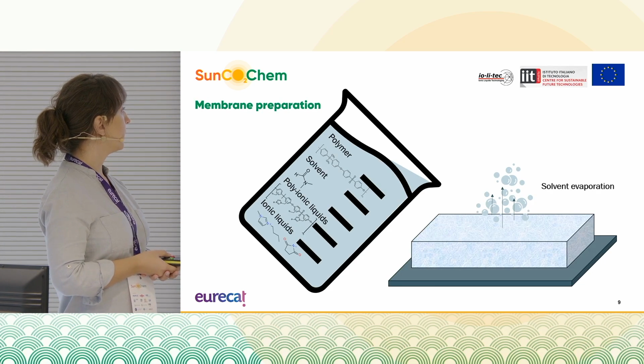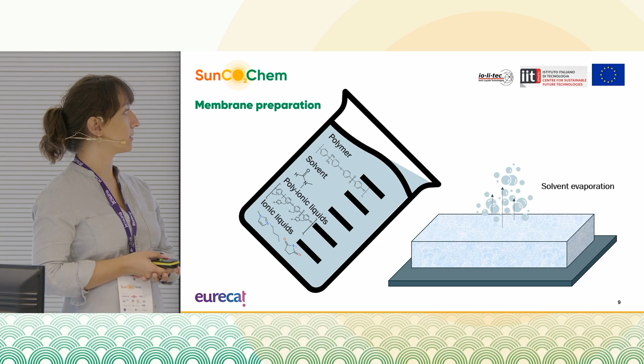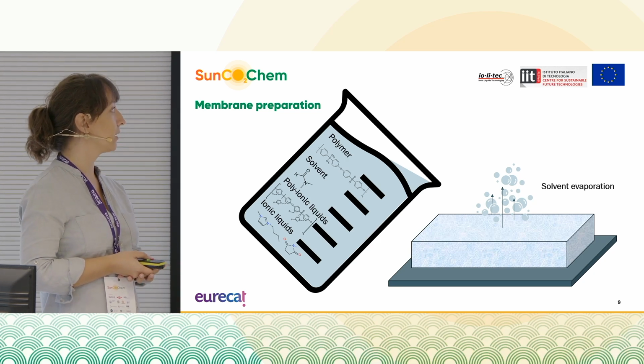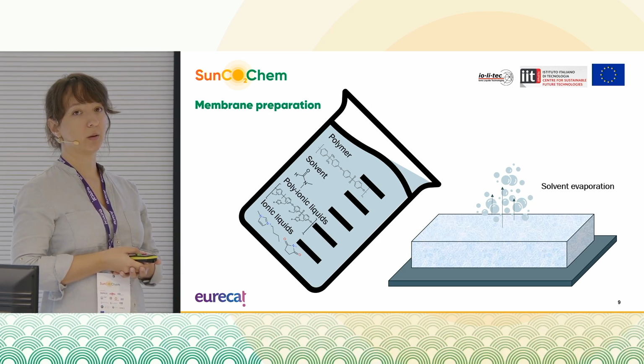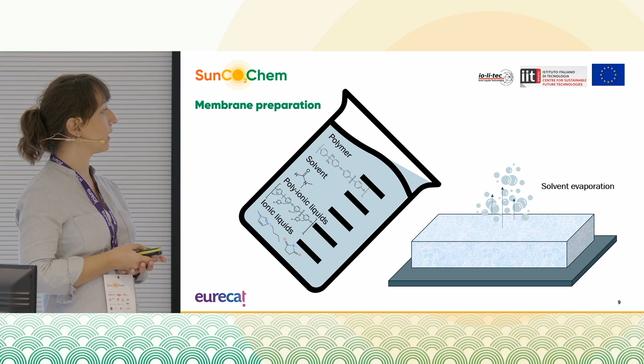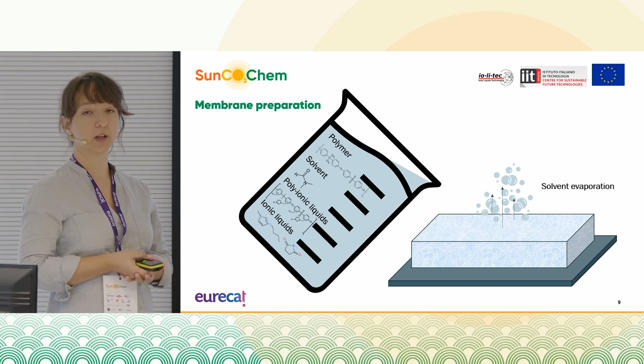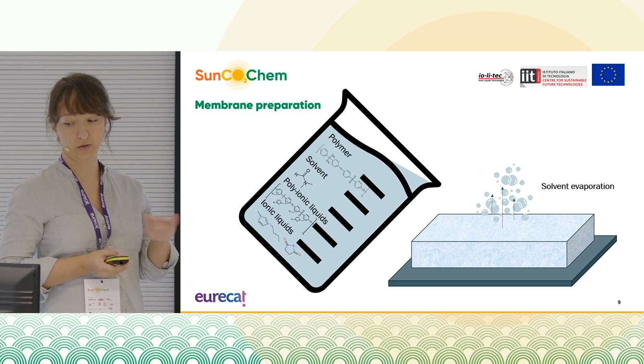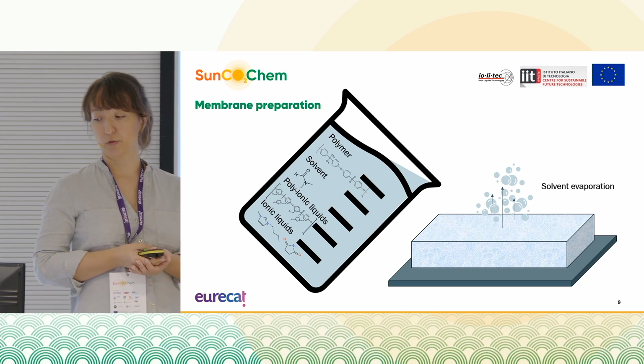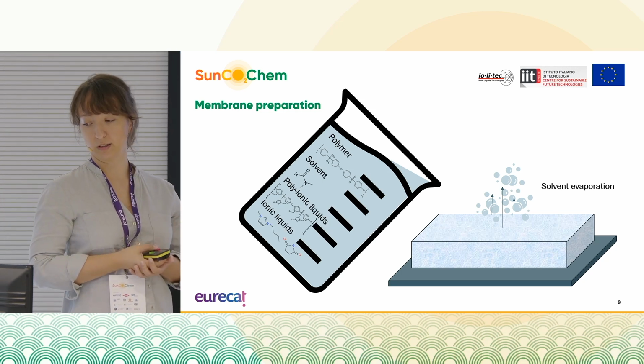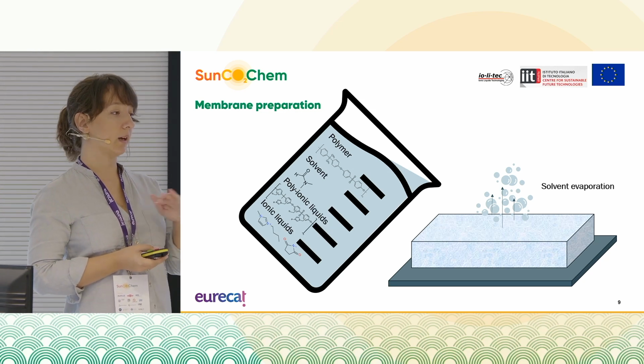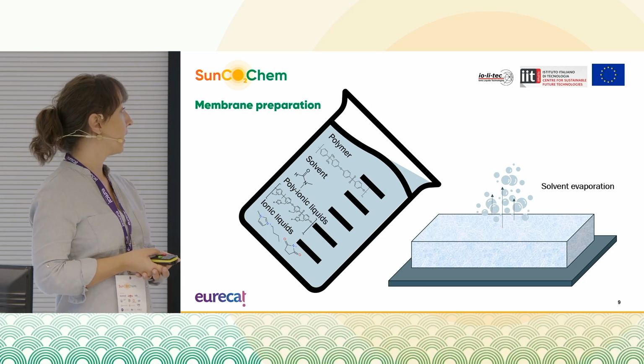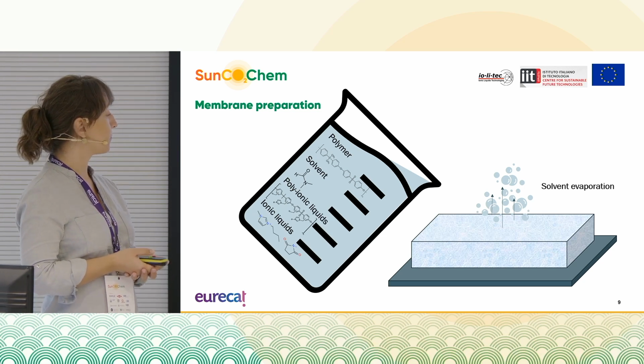The membrane was prepared by a solvent evaporation technique. In this technique, we prepare a polymeric solution, then we cast it on a support. In our case, it was a glass surface, and we leave it for the evaporation under fume hood in order to obtain a continuous film and a solid membrane.